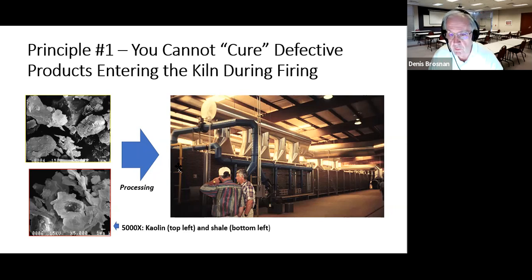And finally, we're going to take them to a kiln. This is a tunnel kiln. These gentlemen are standing beside a very long tunnel kiln. And so you can see the ducts on top of the kiln where air movement is taking place. This is the cooling zone of the kiln because air is being blown down to remove heat from the product as the product goes, in this case, from your right to the left in the processing step.